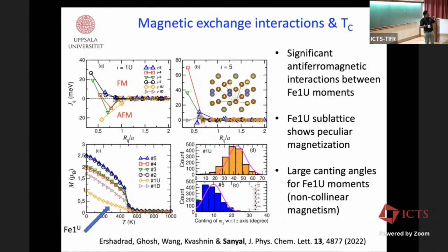And there are so many sublattices. If you look at this one here, the central site is one iron atom in the iron 1 up sublattice, okay? And then with that atom, the different pairs of atoms have been considered and the exchange parameters have been calculated. So many of them have ferromagnetic character, but you also see that some of them have antiferromagnetic character,